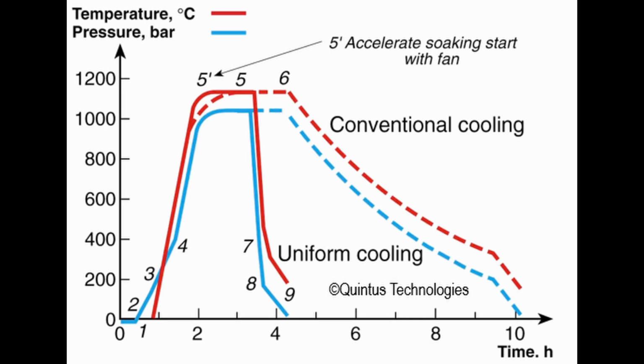And it's also a little bit connected to the amount of pressure that you need and the temperature involved. So the higher the temperature and the higher the pressure, of course you have to do more pumping, more heating, etc. But then usually in the specifications, they talk about the whole time for the HIP cycle. So if it's maybe 2 hours at 900 degrees C, 1000 bar, this is a kind of typical titanium cycle. Those kind of standards are out there.